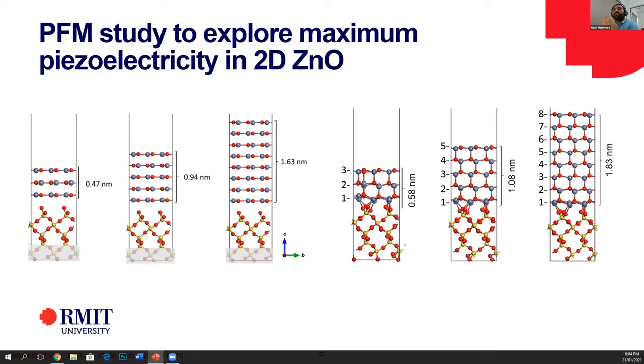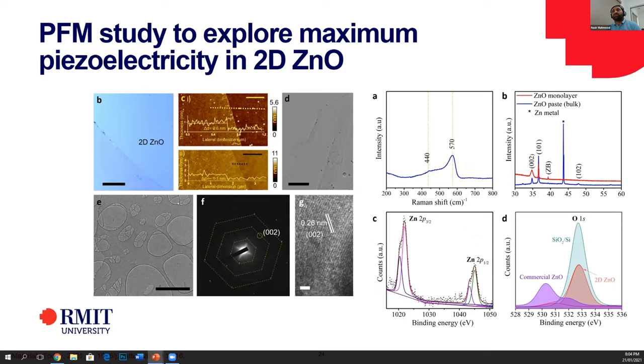the size of zinc oxide. Previously, no one had studied whether reducing the thickness of zinc oxide can give such performance. So in the next slide, I will show some of the characterization of my material. You can see it's a very large sheet. You can produce millimeter, centimeter, or even as big sheets as you want with our method. They are ultra thin, unidirectional in growth, and highly crystalline. And XPS shows that there is a covalent connection between the zinc oxide and silicon dioxide.